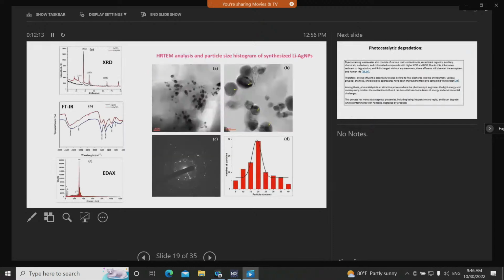Now, this is the analytical characterization. As we can see, this is the XRD spectrum with 4 diffraction peaks, which are similar to the standard AgNPs. And this is the FTIR of lignin and the lignin-mediated silver nanoparticles, which shows the stretching of various functional groups related to the lignin biomolecules. And this is the EDX. It shows a strong peak of silver, which indicates the presence of silver nanoparticles, along with some minor components such as carbon, oxygen, sulfur, and chlorine, the biochemical components of lignin, confirmed through the EDX.